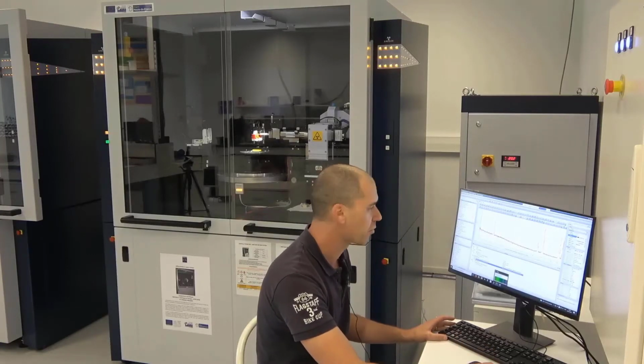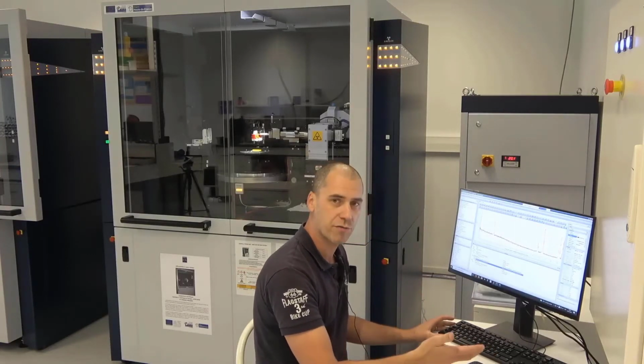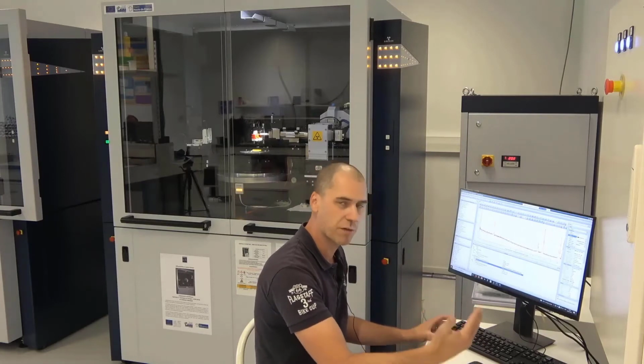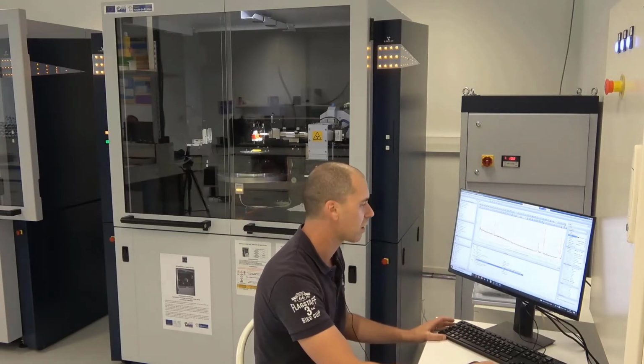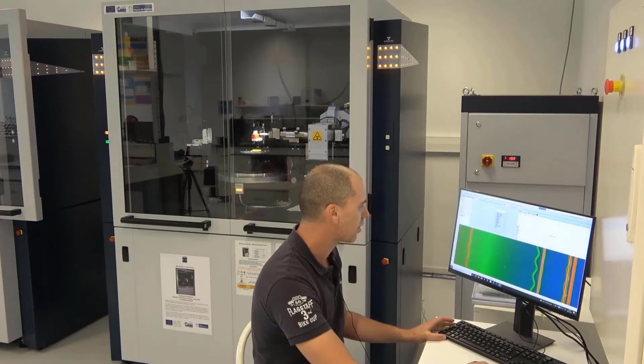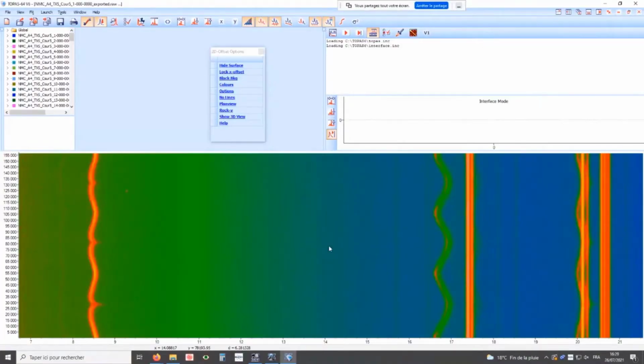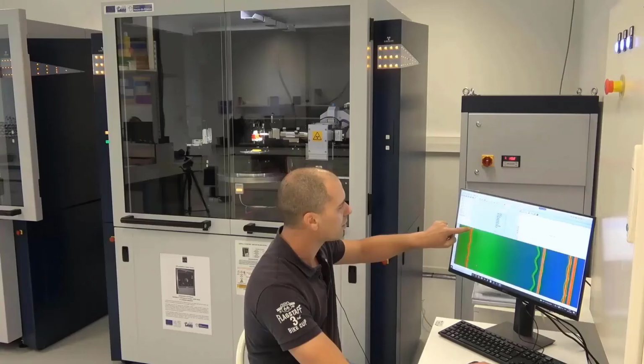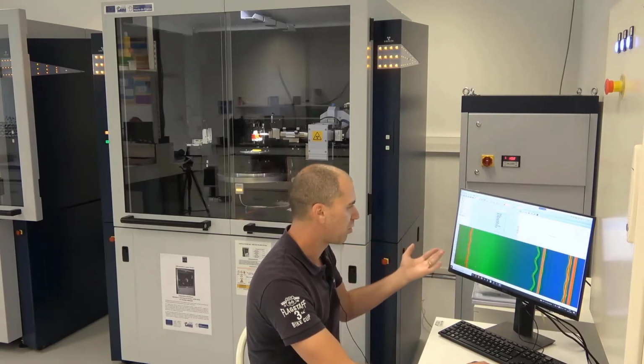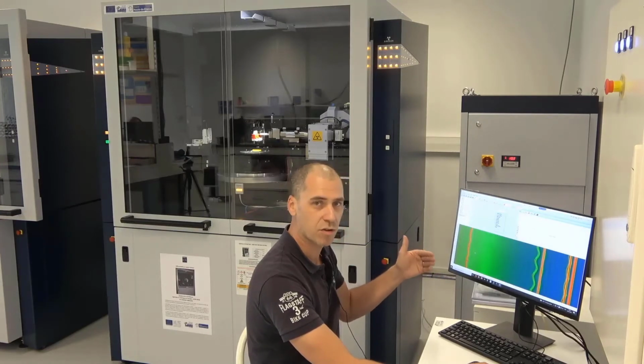So as I just said previously, we can measure a lot of different powder patterns one after another using the snapshots mode. And here is an example on the same material, this is a classical NMC cathode material. And we can see here the evolution of the 00L lines as a function of the cycling of the material. So we can follow in a very short time scale the evolution of the material.